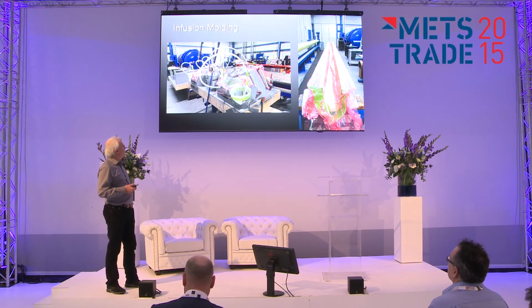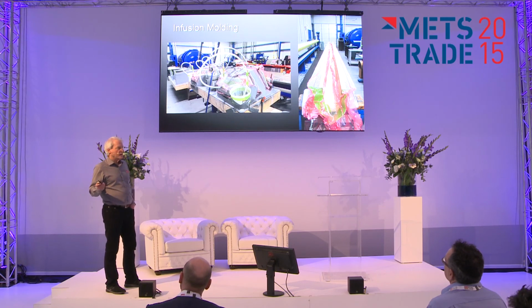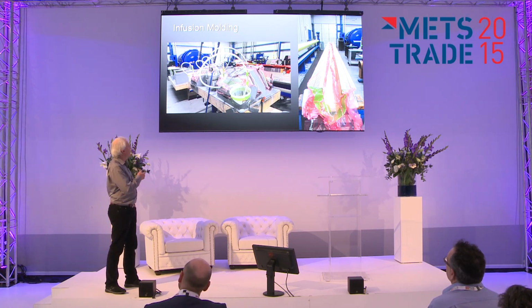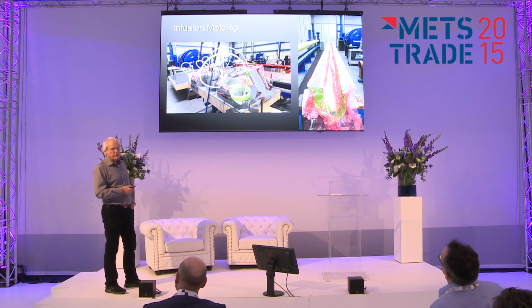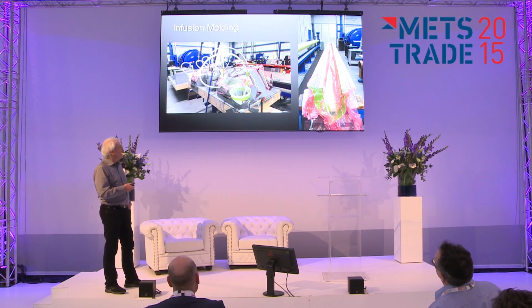We also use infusion. It's just one of the things we use, but there are so many methods in advanced composites. I could go on all day about it, and you'd ought to be either out of here or asleep. But with infusion, these tubes are hooked up to a vacuum pump, and it just sucks. You start out with a mold with dry material in it, and the vacuum pump sucks liquid resin in, usually much thinner or runnier than normal epoxies, which are kind of thick when you mix them up. They have to be pretty runny to work through this, and there are special epoxies that do it, and they're generally ambient temperature cure, but we use them for molds to make advanced composite parts in the autoclave, and for making the molds, this stuff really is beneficial.